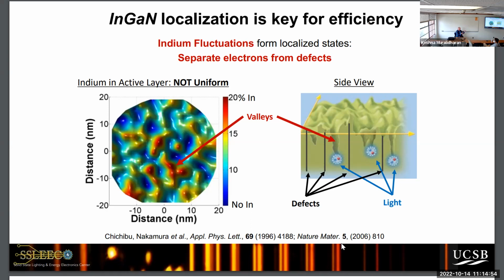but you've got to grow it under conditions where you get indium gallium nitride, where you get some localization. And another thing people do in telecommunication devices I worked on is, with indium, they make quantum dots. So you get a surface that's not wetted and the indium will ball up. And so then you cover that up and you get what's called a quantum ball or a quantum box. So that's also used in telecommunication devices. It's called a quantum dot laser. So this is now being used not only in the nitrides, but also in the indium phosphide materials.